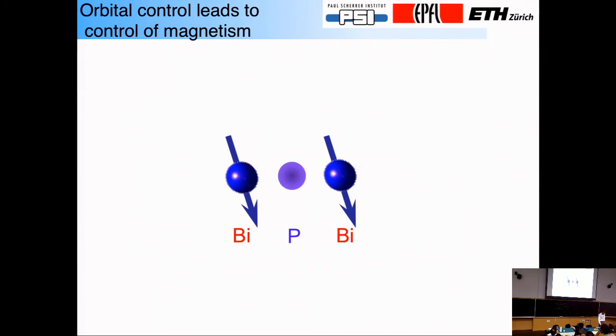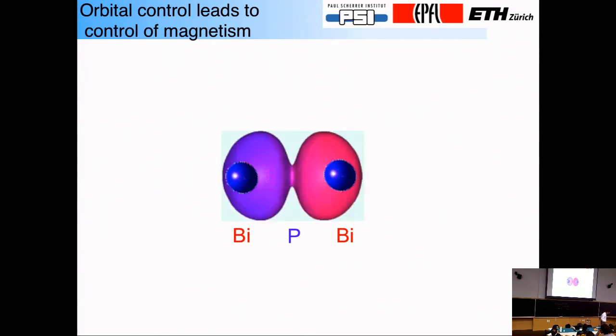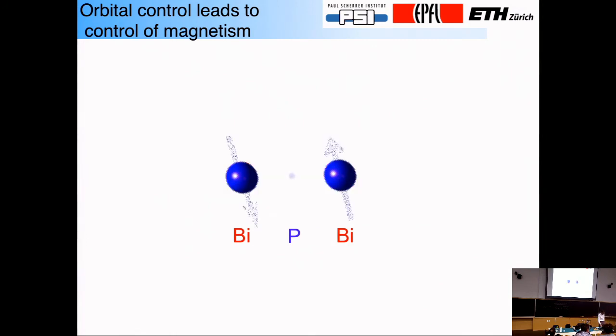If I come along and coherently excite the phosphorus with a terahertz pulse, then the wave function of that phosphorus expands to have substantial overlap with, let's say, the 6p wave functions of the bismuth atoms. Because it's a coherent excitation, it's clocked, and I can have a timed exchange interaction between the bismuth spins. So after the pulse is gone and I've de-excited coherently, I can be left with the spins in opposite directions.